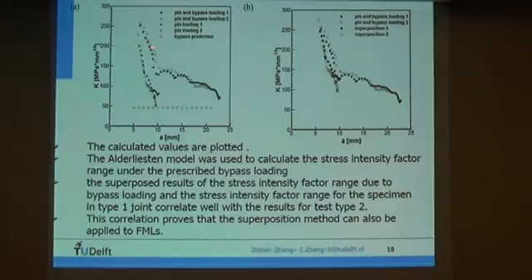This upper line is from the test type 2, and this line is from the pin loading. And for this line, we use the Alderliesten model to calculate the stress intensity factor for the prescribed bypass loading. So we add this line with this line, and we can shift this line here. The superposed result of the stress intensity factor range due to the bypass loading and the stress intensity factor range for the specimen in test type 1 agrees well with the result of test type 2. We can see the two lines match very well. So this correlation proves that the superposition method can also be applied for the fiber metal laminates.